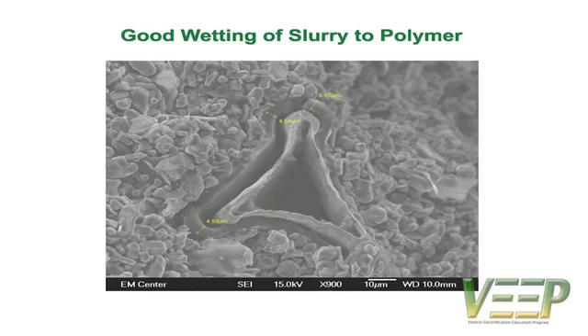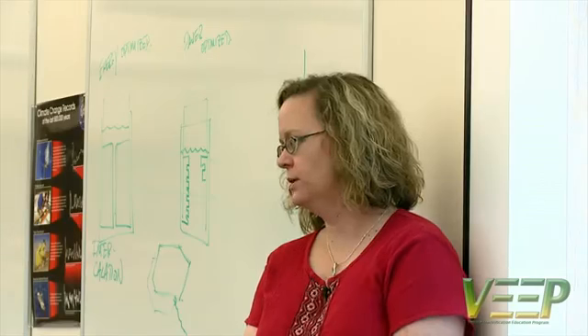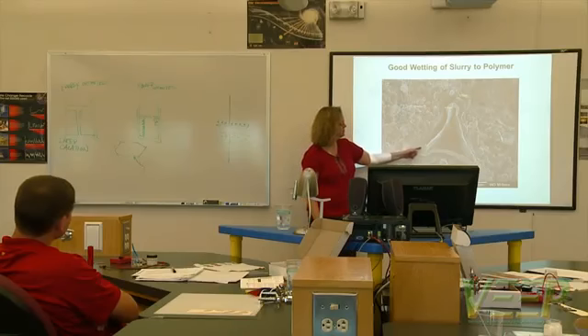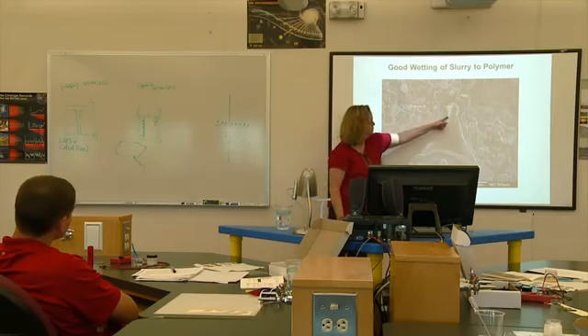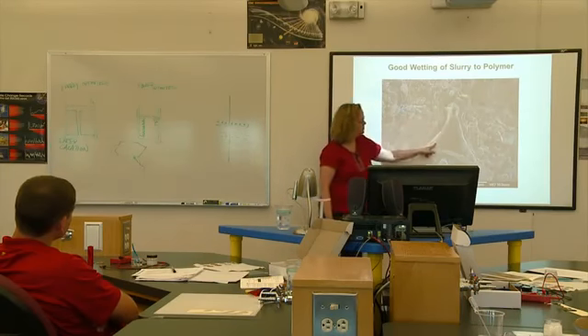And what happened here is we took the whole thing, we froze it in liquid nitrogen and cracked it so we could image it. And we noticed that when we froze it, the polymer pulled away. This is the copper antimonide here. This is the copper foam.